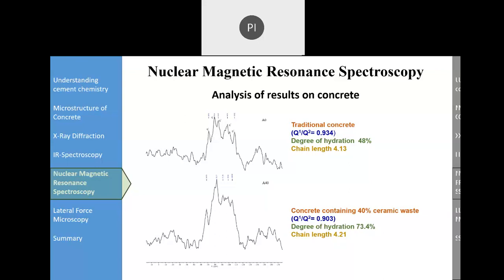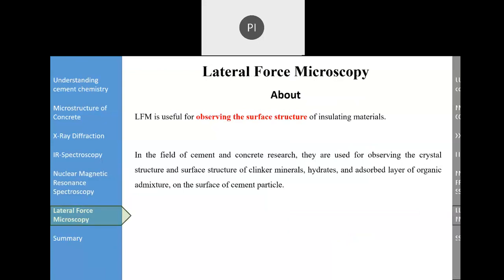Like here, we are quite confident that when we are using 40% ceramic waste as a replacement of fine aggregate, not only we are getting more reaction, more degree of hydration, but a higher bond chain length also. Then it's quite obvious I'll get all the properties better. And it also happened when we tested for mechanical properties and durability properties. Everything was better than the traditional concrete.